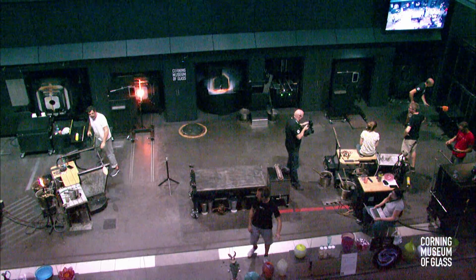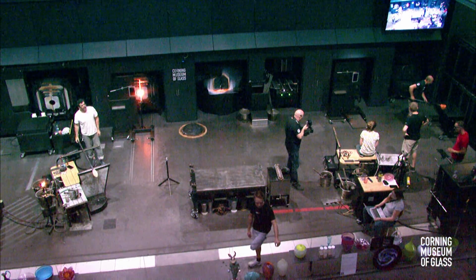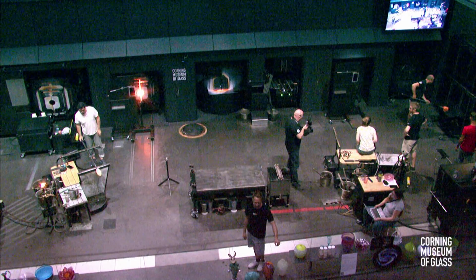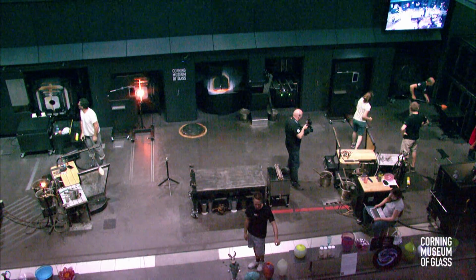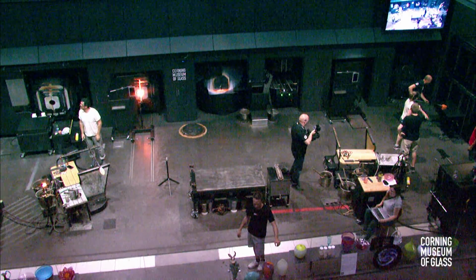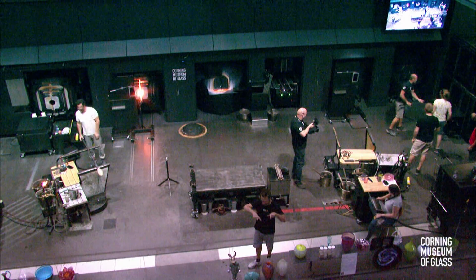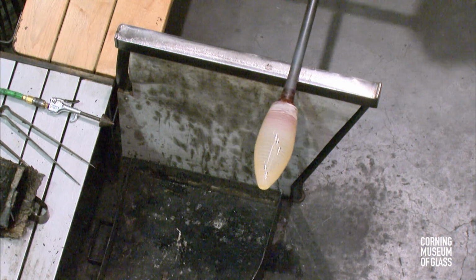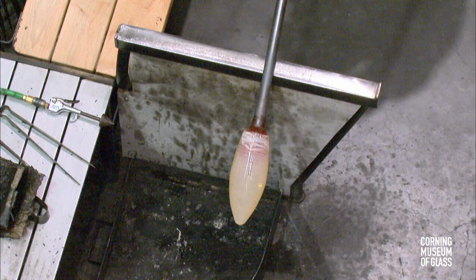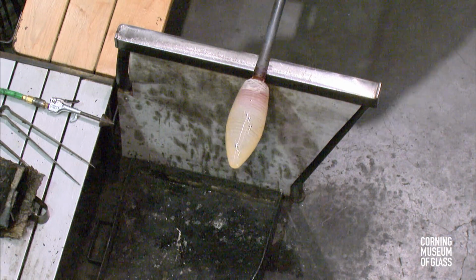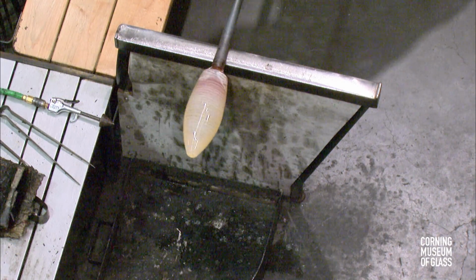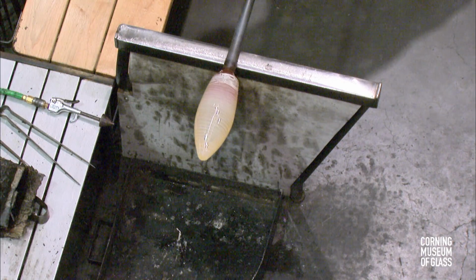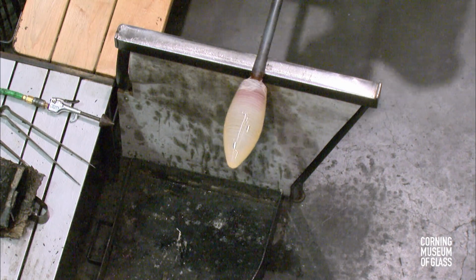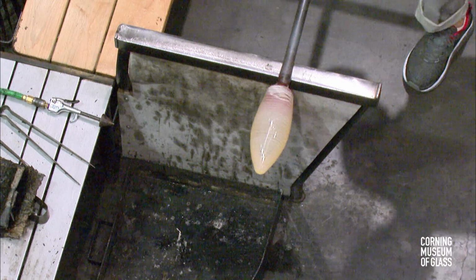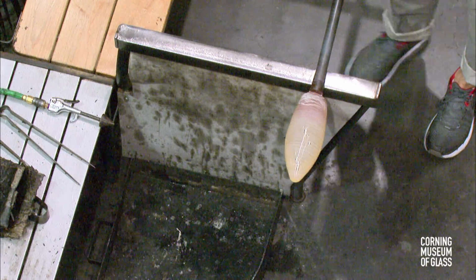The ribbon machine now produces light bulbs pretty fast. About 1,600 bulbs per minute are made with the ribbon machine. And it's literally a machine that just drips a hot glob into this ribbon mold, if you will. It's shooting sideways, and all these little gobs drop in this little hole, and they drip with gravity at just the right temperature, and they blow up with air, and you create this perfect light bulb shape out of them, and they just pump them out, just cranking them out.